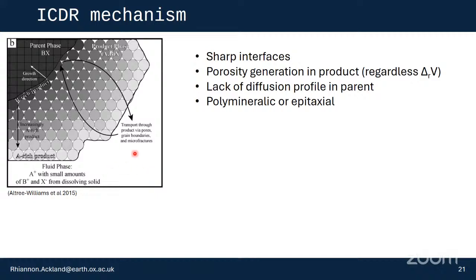The classic example of this is where you have a parent phase, BX, which is in contact with a fluid rich in a different cation, A, and these react to form the product phase, AX. Rather than a diffusive exchange of A and B between the fluid and the parent, they suppose that the outermost layer of the parent phase dissolves in the fluid, and this causes saturation of the product phase and precipitation of that product phase. And the rates of this dissolution and precipitation are coupled. This reactive interface then moves throughout the crystal, slowly converting it to the product phase.